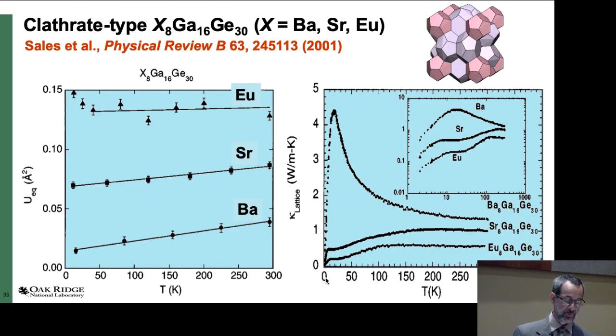So the temperature dependence and the 0 point values for a series of these clathrate structures where you have europium, strontium, and barium in a large cage do not follow the expected behavior based on mass. In fact, what it seems to follow is the relative size of that atom. So barium is bigger than strontium, bigger than europium. So the intercept here corresponds to a positional disorder or a split site. And also they're loosely bound, so they have very large amplitudes of displacement. And we've been able to correlate these with the lattice thermal conductivity, particularly glass-like behavior for the europium and strontium.